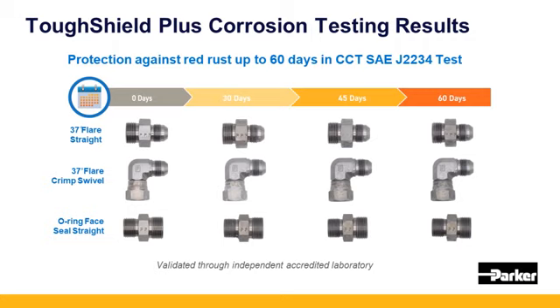Now, this is a similar sort of grid, but for the cyclical corrosion. We're showing a 60-day CCT test to the SAE J2334 testing. So again, the same takeaway here from 0 all the way to 60 days. That represents one full cycle of this fairly demanding test.